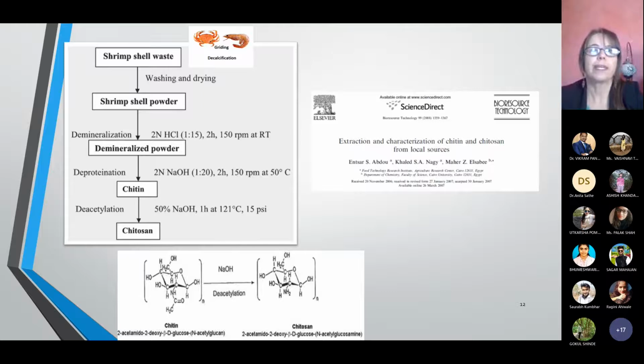Then the first step is the demineralization. This step was carried out at room temperature using hydrochloric acid baths. Here I have to say that the number of baths and their duration will depend upon the source. It was observed that CO2 gas was emitted, of course, due to the elimination of mineral materials.